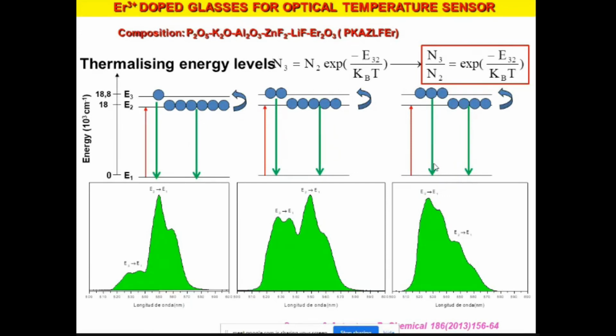See, sensors are really an equally important field of research, and that you can do with rare earth doped glass also. For example, a rare earth ion is doped in some matrix. At normal room temperature, this is the ground state, this is the excited state, and these excited states are very close together. I mean, these two levels can be thermally populated. These two, E2 and E3, separation is so small that this can be thermally populated, and the relative population depends upon the temperature. At room temperature, this level is densely populated, this upper level is less populated.